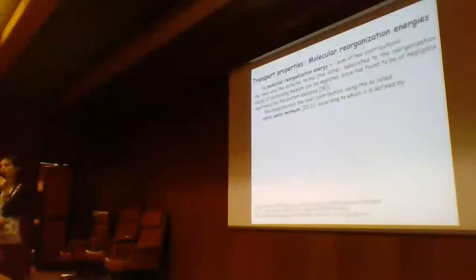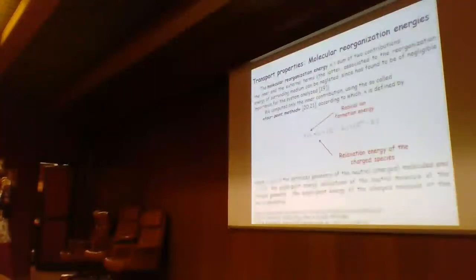We have computed the molecular reorganization energy, lambda, which is the sum of two contributions, the inner and the external terms, but we only computed the first term because the last one can be neglected. The method used is the 4-point method, according to which lambda can be defined as the sum of the radical anion formation energy and the relaxation energy of the charged species, as the following expression shows.